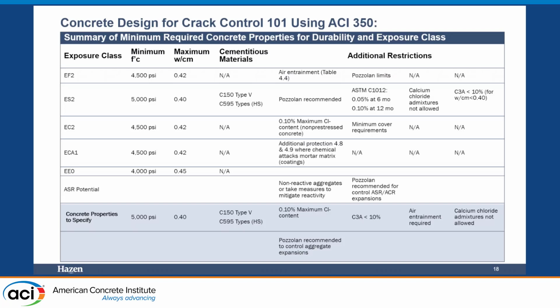For this particular example, we would also need to look at type 5 cements or type HS 595 cements. We also have maximum chloride restrictions, air entrainment requirements, and pozzolans would be recommended to help control aggregate expansions. I've not included on the slide some additional pozzolan restrictions relative to maximum and minimums, depending on your freeze-thaw. That is just a little bit more than what we were going to cover.